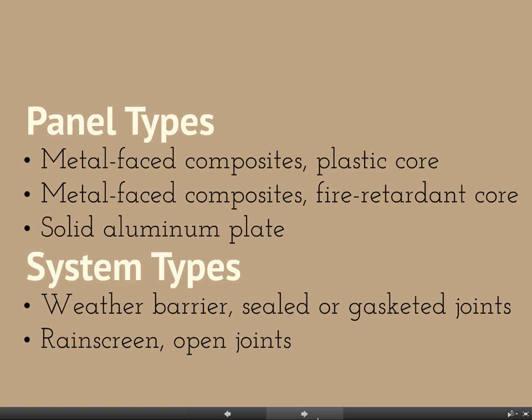And she asked, was one of them a 2-coat and the other one a 3-coat system? Oh, that I couldn't tell you. I think that they were specified as the same, but because they were applied differently, they ended up appearing differently. Because with a spray, the particles will all be scattered, obviously non-directional, whereas a coil coating tends to lay them up more directionally, if you will. That's my understanding of it, based on everybody arguing about it for a really long time. Okay. Well, thank you for sharing all that.